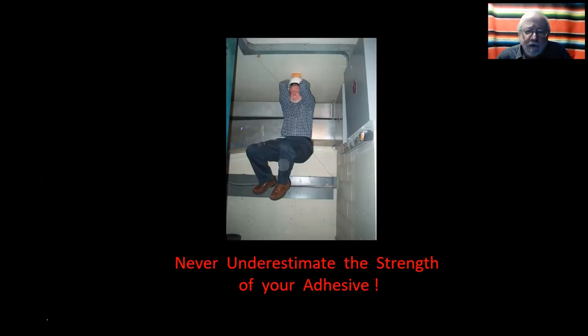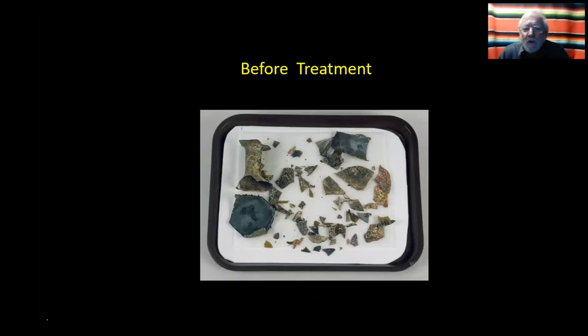I've tested the strength. DuPont has tested the strength of B-72 and the Getty has tested it. And we've all come up with about 200 to 600 pounds per square inch, which is plenty strong enough to hold any kind of glass together. And how do we glue it together?